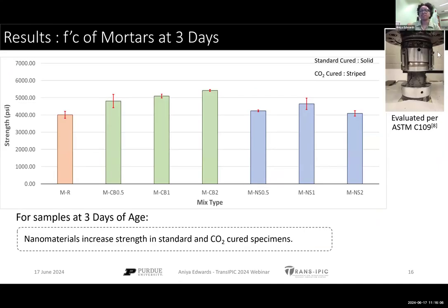So for our 3-day compression, what we found is that when looking at our reference material, which is shown on the left in orange, we can see that carbon black and nanosilica does help improve that 3-day compressive strength. The highest improvement is seen in the carbon black at 2%. However, what was interesting was that we're not necessarily seeing a linear increase in strength with our nanosilica samples. There's actually kind of a peak occurring with nanosilica at 1%.